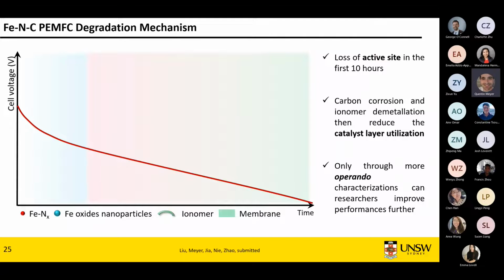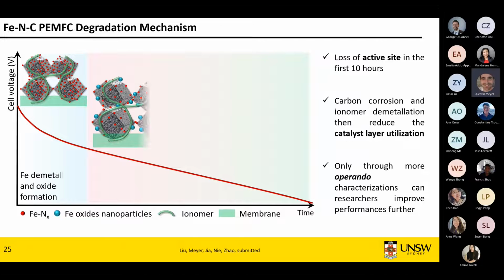So overall, we've got this kind of mechanism happening at the moment. First step, this is your catalyst layer structure. I've got a schematic, you can imagine a lot of little iron-nitrogen-carbon active sites. You've got some Nafion ionomer that's creating proton pathways. And the first step of degradation is you have basically iron demetallation and oxide formation. So you have more and more oxide particles covering the surface. You've lost a lot of active sites. Your ionomer still looks overall the same.